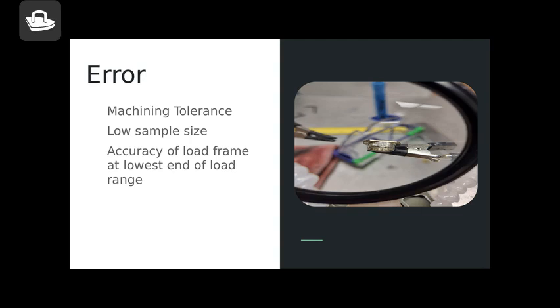And finally, the load frame is rated to 100 kilonewtons of force in the load cell, and we are very close to the bottom end of its capacity, running at a max of 500 newtons. So it's unclear whether the calibration of the load cell was accurate in the ranges that we're working in. So using a more appropriately sized load cell could have yielded better results as well as the forces applied to the system could have been better verified as completely accurate.